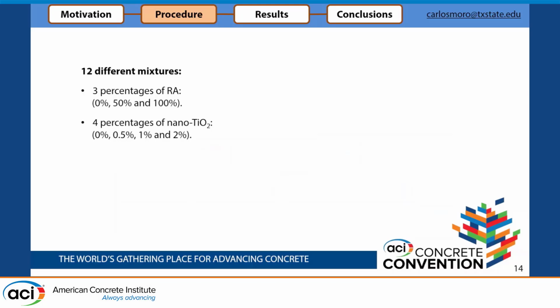For this study, we used 12 different mixtures with 3 percentages of recycled aggregate. That means natural aggregate 100%, 50-50, and then 100% recycled aggregate, and 4 percentages of nano titanium dioxide from 0 to 2%.